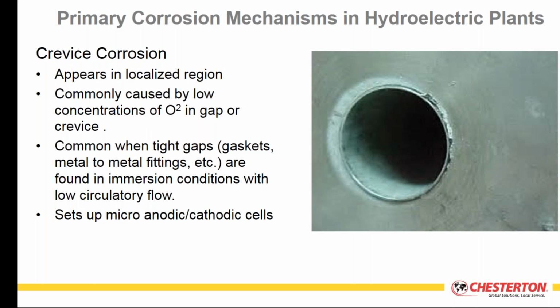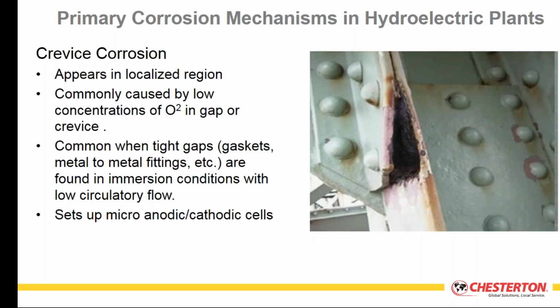An example of this in a heat exchanger system would be the welded joint between the tube and the tube sheet plate. That small crevice region becomes depleted in oxygen. You'll get active corrosion cells generating in there, where areas are becoming more anodic than cathodic, and that precipitates the corrosion. You may also see it in structural steel reinforcing areas where you have these gaps on riveted structures or skip welded structures. Those gaps become zones, again, of low oxygen concentration. You'll get oxidation occurring and corrosion occurring.